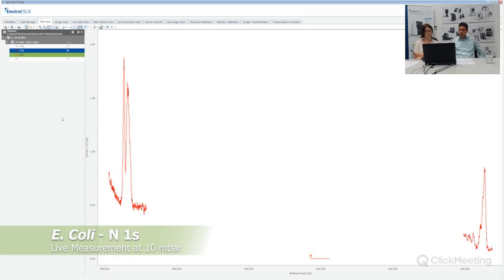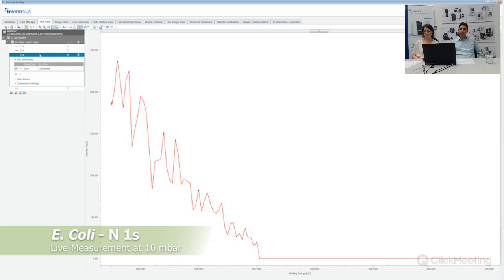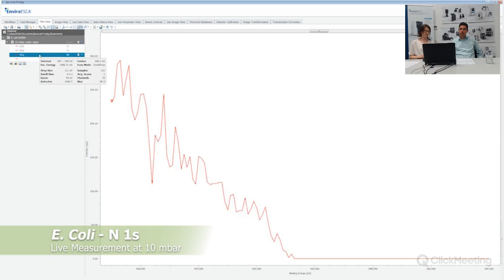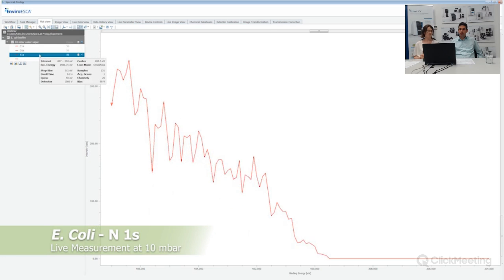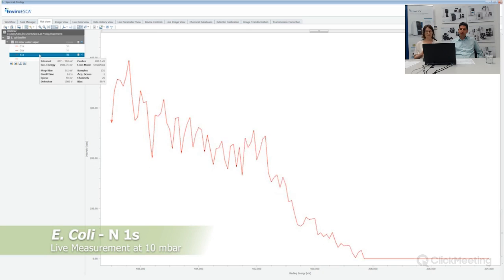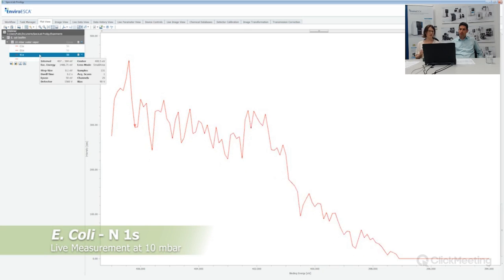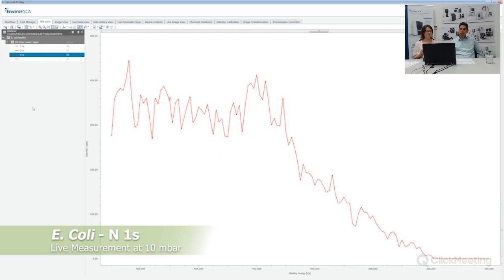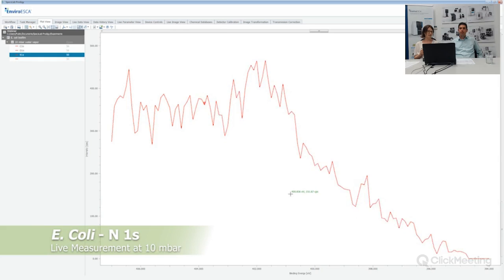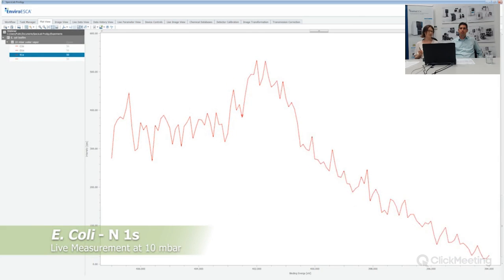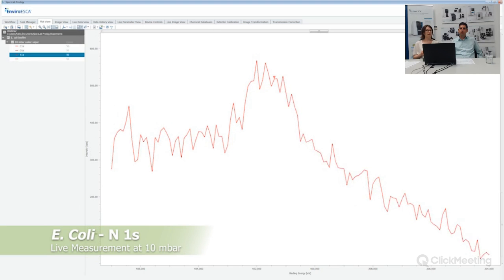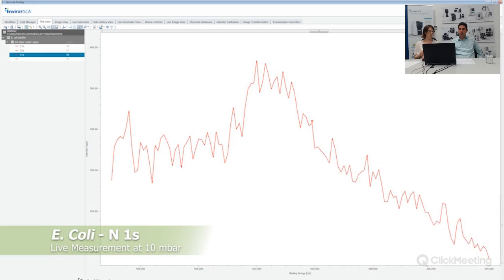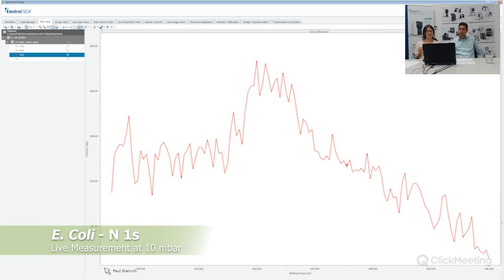So the next spectrum will be the nitrogen from the sample itself. The signal for nitrogen mainly comes from proteins, which are made of chains of amino acids. You also have amine groups in various amino acids, but unfortunately we are not able to distinguish the amines from the amides. They are both at 400 electron volts. However, at higher intensities we also see a peak from protonated nitrogen species, approximately 1.3 electron volts shifted towards higher binding energies.